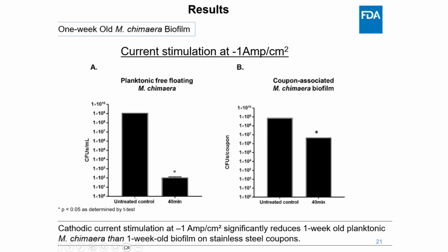As with the earlier experiments, we saw a significant reduction in planktonic cell viability compared to the growth control. However, when we examined the biofilm-associated cells on the stainless steel coupons, the effect was more limited. We observed only about a 2 log reduction in viable cells in this 1 week old chimaera biofilm treatment.